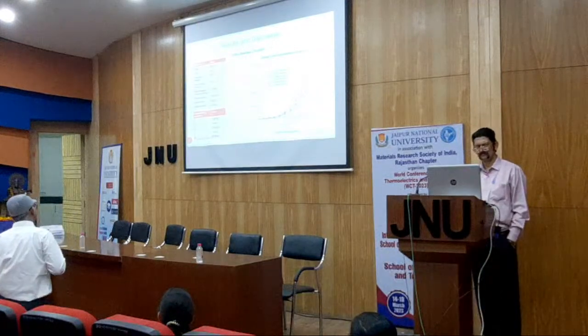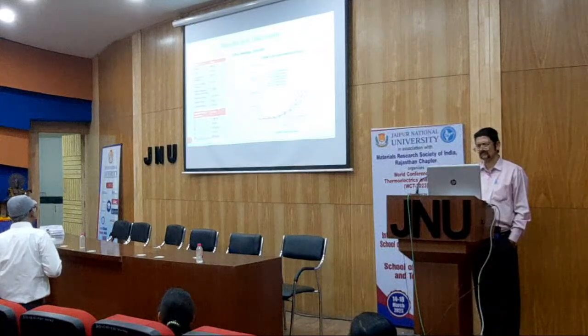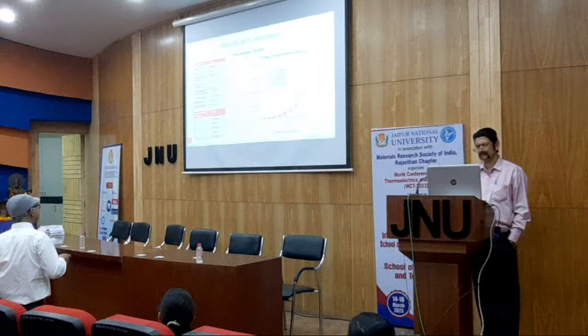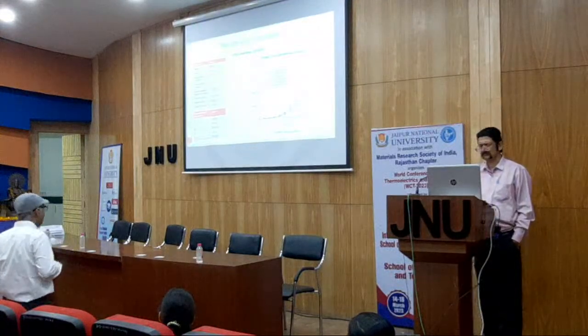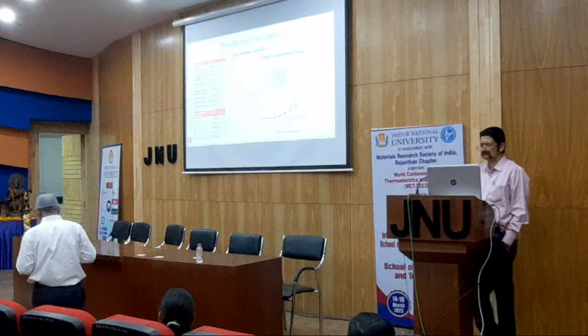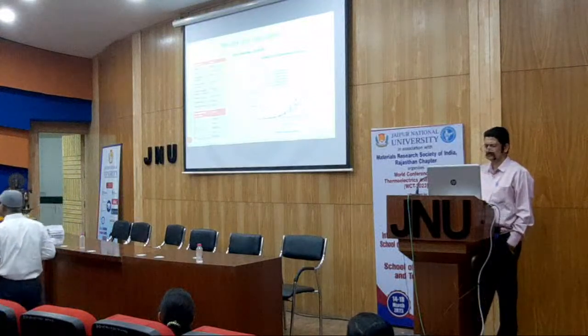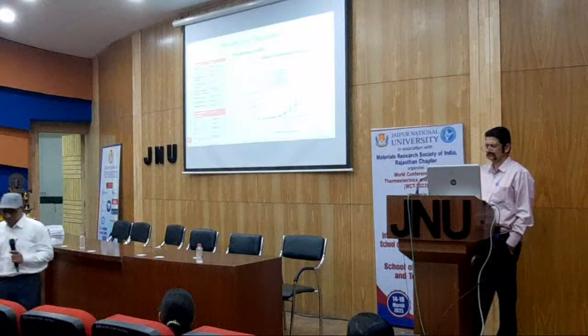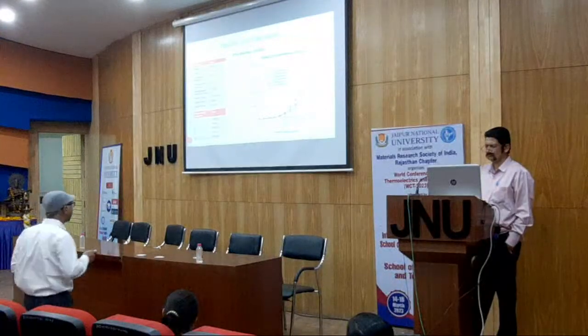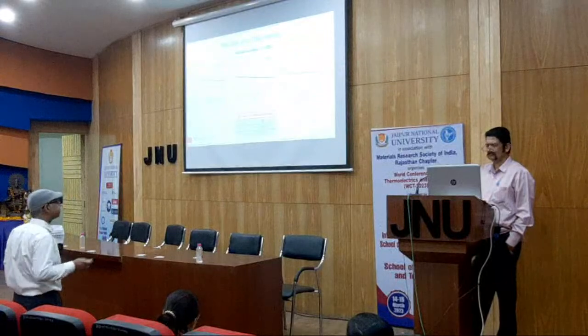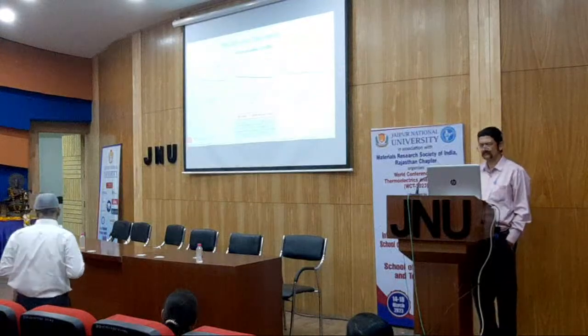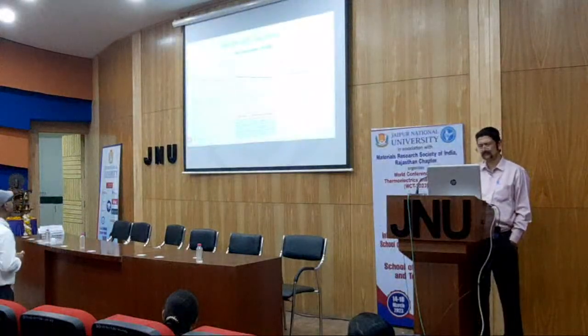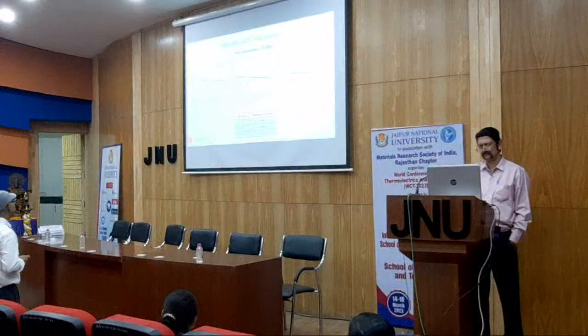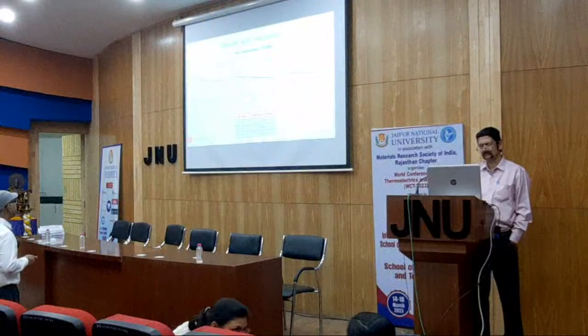Now these are the final physical dimensions, and these are the model fitting curves. The dotted points are the model fitting curves, and the straight lines are the experimental results. The ultimate target was to make a super model that can model the electrochemical behavior as well as the semiconductor behavior. That we performed, and you can see this is matching quite well. Next please. Drift analysis, as I said, has semiconductor parameters as well as electrochemical parameters. So in that case, how the drift varies with time was also analyzed, and these are the results which were measured. Next please.